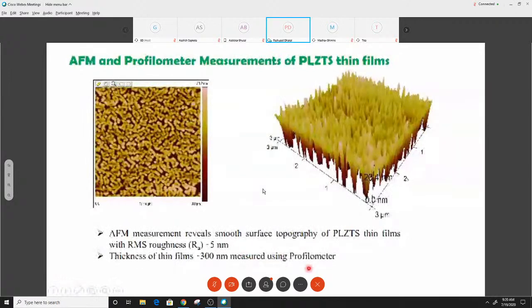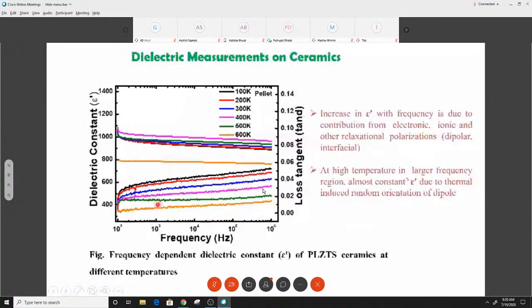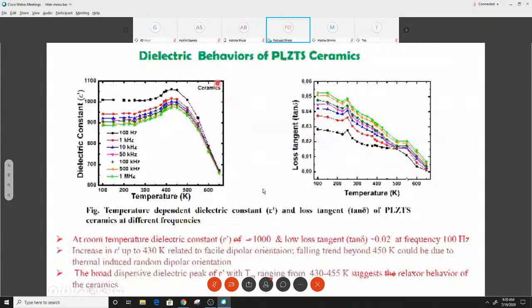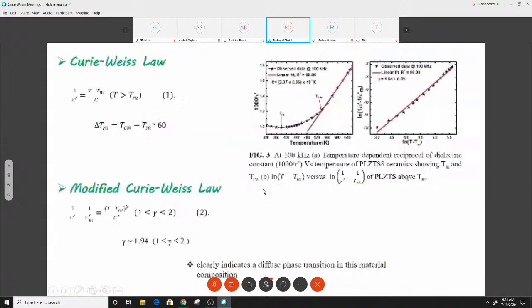This is the dielectric constant with frequency of the ceramic capacitor. We got a dielectric constant of around 1000 at room temperature at 100 Hertz frequency, and we got a low loss tangent. This is the dielectric behavior of the PLZTS ceramic with temperature. So we can see a broad range of dielectric constant with temperature, and it gives insight into the relaxor behavior of the materials. Further, we analyze the relaxor behavior quantitatively, and we got delta Tm equal to around 60. It shows the relaxor behavior of the materials.